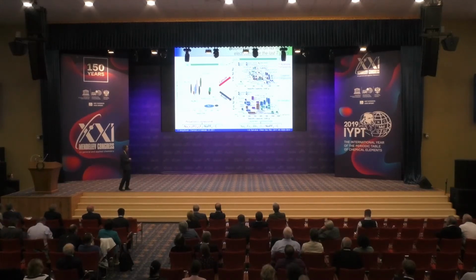So what we are looking at is this type of system where you have, in this case, this NVPF, which is Na3V2(PO4)2F3, and carbon. And when you look at the voltage-composition curve, you have this cell voltage as a function of capacity, which outputs a voltage of 3.6 volts. If you look here, you have huge irreversibility, which is due to the consumption of sodium by this SEI layer. So in order to bypass this issue, we need to design new materials in order to bring enough sodium into our system.